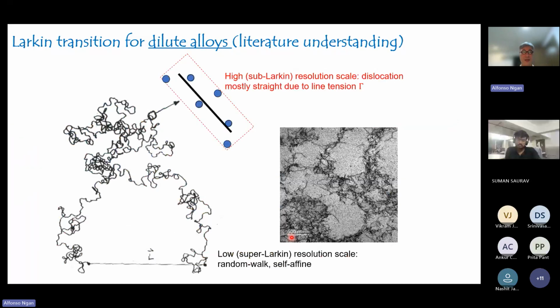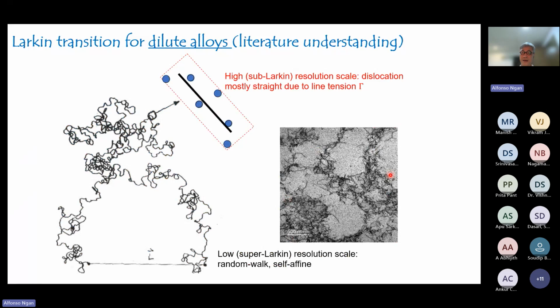Okay, so that's better illustrated in this slide. This is a typical TEM image of a dislocation cluster in a mildly deformed sample. If you pick any dislocation out, you would agree that the dislocation at this low resolution would be very wavy. In fact, people have done analysis to show that sometimes it exhibits self-affine geometry or fractal geometry, or some people call it random walk. But if you zoom in on a very tiny part of a dislocation, at a high enough resolution, the dislocation line would tend to be straight. Well, this is the literature understanding, right?